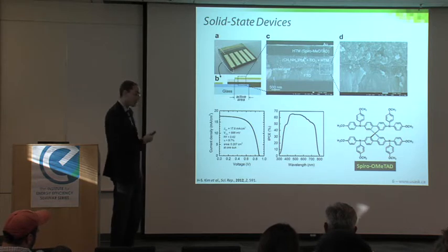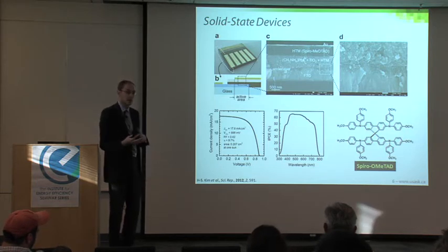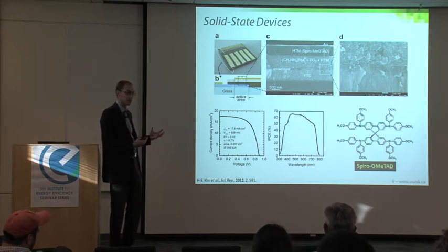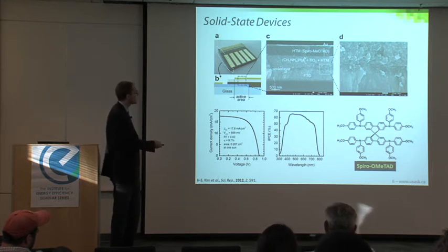The problem with perovskite is that it was actually dissolving in the acetonitrile electrolyte. So it's actually kind of amazing that they were even able to get 3 or 4% out of those first devices. But if you switch to a solid-state hole conductor like spiro-OMeTAD, you no longer have that issue. Gratzel was able to prepare devices with efficiencies of about 10%.